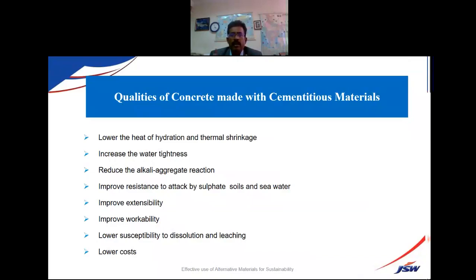Concrete made with these cementitious materials has very good advantages. Look at the properties. Heat of hydration is going to be lowered completely by using GGBS. Water tightness increases. A paper has recently been published, it has come today only. I'm going to share it with all of you. We have done high volume GGBS concrete for marine structures, where we studied all these parameters: water tightness, sulfate resistance, and chloride resistance. I'm going to share that article with all of you after the presentation is over. Overall, the cementitious materials are going to improve the performance of the concrete, workability, and at the same time, it comes at a lower cost. Since it's an industrial byproduct, you have to process it, and it is always relatively cheaper compared to clinker or pure OPC cement.